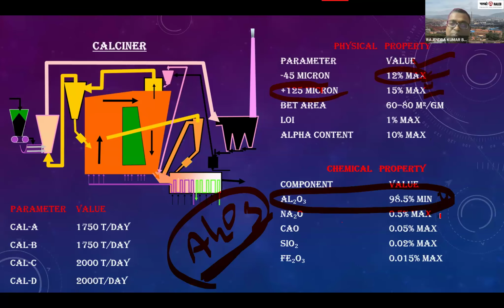Na2O is 0.5% maximum. CaO, calcium oxide, 0.05% maximum. SiO2 0.02 maximum. Fe2O3 0.15. 98.5% minimum we are getting. We are getting more than this sometimes, 99 something in our alumina.